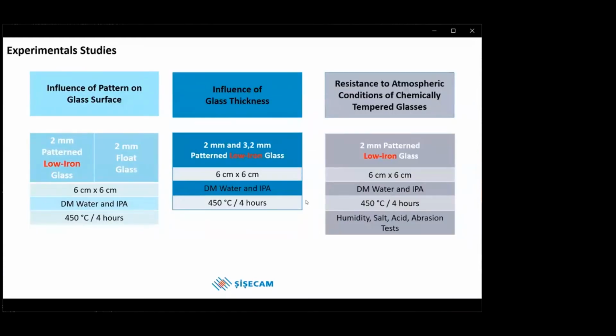Let's look at our experimental studies briefly. In the study where we examined the chemical tempering behavior of patterned low iron glass, we cut our glass samples to a certain size and then cleaned them with demineralized water and isopropyl alcohol in ultrasonic baths. We carried out the chemical tempering process at 450 degrees for 4 hours. Time and temperature values were selected in accordance with the information obtained from the literature and experimental studies we have done before. Then the results were compared with the results obtained in the study with float glass.